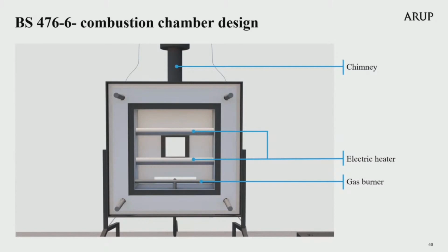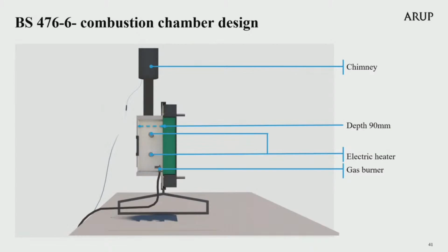On screen now is a close-up of the combustion chamber showing the 3 heat sources, 2 electric heating elements and a gas burner as shown. The internal dimensions of the combustion chamber are 190 millimetres by 190 millimetres and a depth of 90 millimetres. I show a cross-section on the next slide. At the top of the combustion chamber is a chimney where hot gases can leave the chamber. As indicated by the dashed arrow, the combustion chamber is 90 millimetres deep. It is useful to understand the depth of the specimen holder, which is marked green and attached to the front face of the chamber.